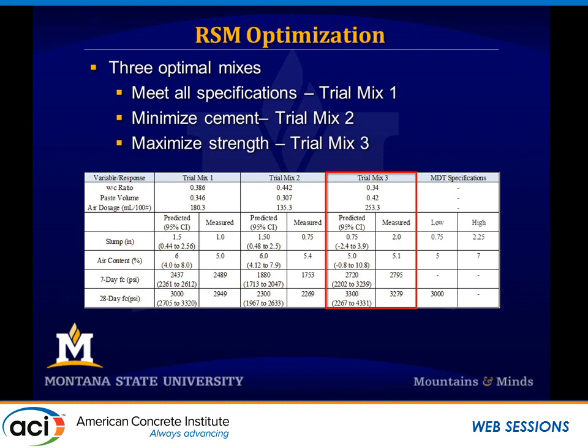In order to maximize the strength, we put the slump at its minimum value, which is 0.75. That's the minimum value that is accepted by MDT. We said, all right, let's dump some of the air to try to increase our strength. So we targeted 5, and then our strength, we targeted 3,300. We were a little off on the slump. Not too bad. Well, right on the air, the predicted air, and then again 3,300 versus 3,279. Okay, so our strengths were right on. So this was telling us, wow, this methodology works pretty well. So that's kind of the conclusion of our little mini study in there, the application of response surface methodology.